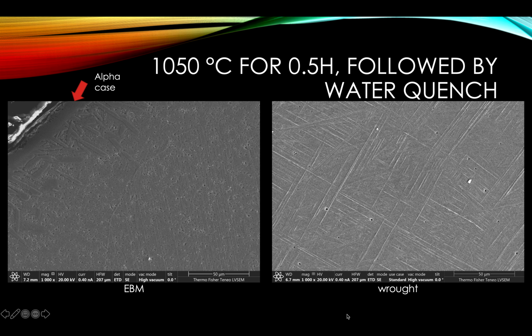Well, for the 1050 Celsius followed by water quench, the alpha case near the EBM sample surface is observed. This is formed during the air exposure during the water quench process. Some needle-like grains are observed. Not very significant, but the predominant grains are globular grains. And for the wrought sample, the martensitic needle-like grains are the predominant ones. That is a very typical microstructure after the beta quench.